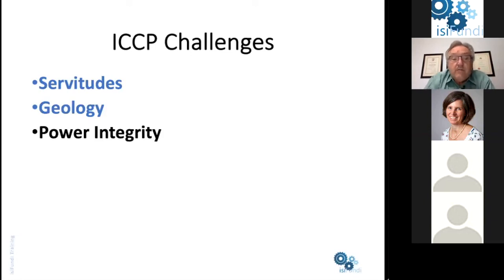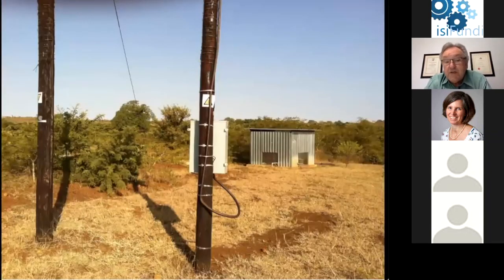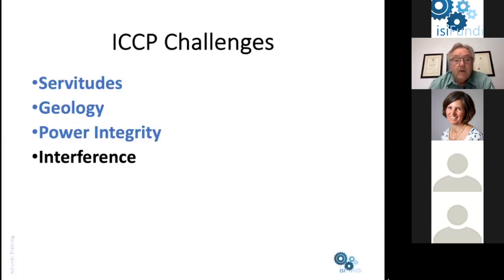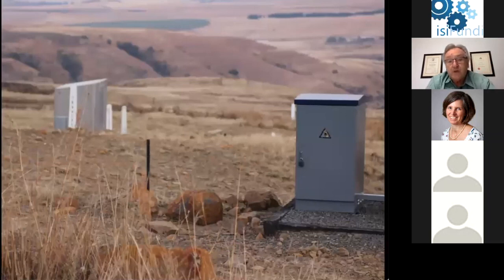We need to make sure that the power is continuous. In theory, grid power is continuous. If it's diesel gen sets, they've got to be serviced and maintained. The integrity of power is particularly important if we have pipeline systems which are subject to electrical interference. On the subject of interference, the pipelines that are protected by impressed current are more susceptible to causing interference. So if you've got two parallel or crossing pipeline systems, you will find that an impressed current system is more prone to cause interference in the foreign pipeline, perhaps than a sacrificial anode system would be.